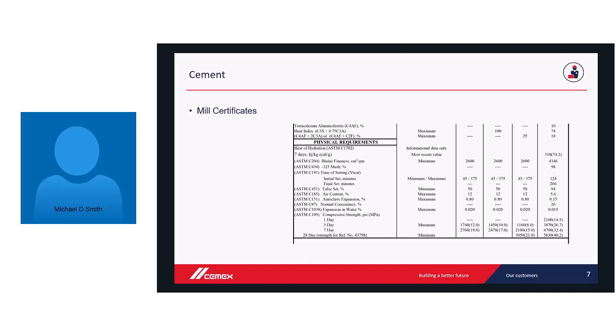If your initial and final sets don't have a lot of time in between the two of them, that doesn't give finishers or suppliers a lot of time to produce and ship and place and finish the product. So those could be a factor when you're looking at a mill cert. False set and air contents, false set, there's certain characteristics where once water comes in contact with the cement, it starts to react, and it acts like it's going to set up and harden right away immediately. Sometimes, depending on whether it's a false or flash set, you can mix through it, but sometimes if it's not, that could be problematic. So you look for those higher numbers, better. So the ASTM standard sets a limit on what those can be.